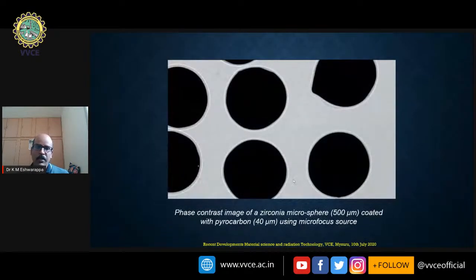Here, actually, it's an image of a zirconia microsphere, which is coated with pyrocarbon, 40 micrometer thickness. Just concentrate on the edges of these microspheres. The coating, you can clearly see that coating of carbon, 40 micrometer carbon. So this clarity we would not be able to obtain using the conventional absorption-based image.